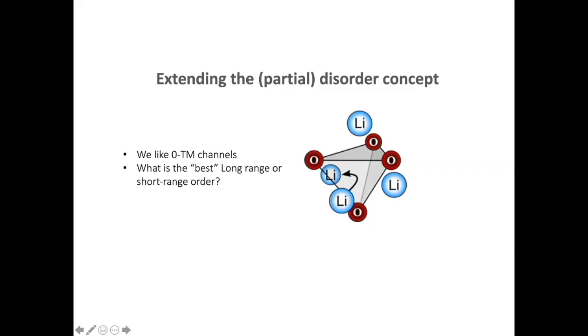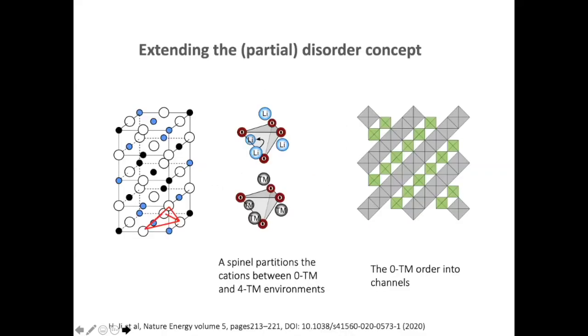So I want to remind you, we like these 0TM channels. They are very good for mobility. So in a DRX material, we rely on them statistically appearing because we just randomized the cations. So we started thinking, could you push the long range order or the short range order in a direction where you make these channels, so not just randomly? And actually, you know, the answer stared us in the eyes, right?